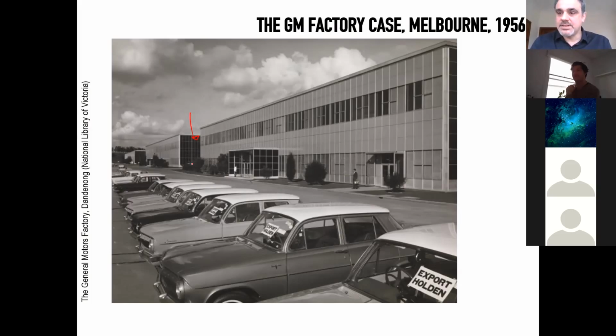And look, what you witnessed there is one case of thermal breakage. So what it is that the glass is subject to thermal variations that are extreme. It's glazed in contact with frame that probably could have been done better. And because of this thermal variation, just a small imperfection on the glass is sufficient to open up a crack and the glass can fall.